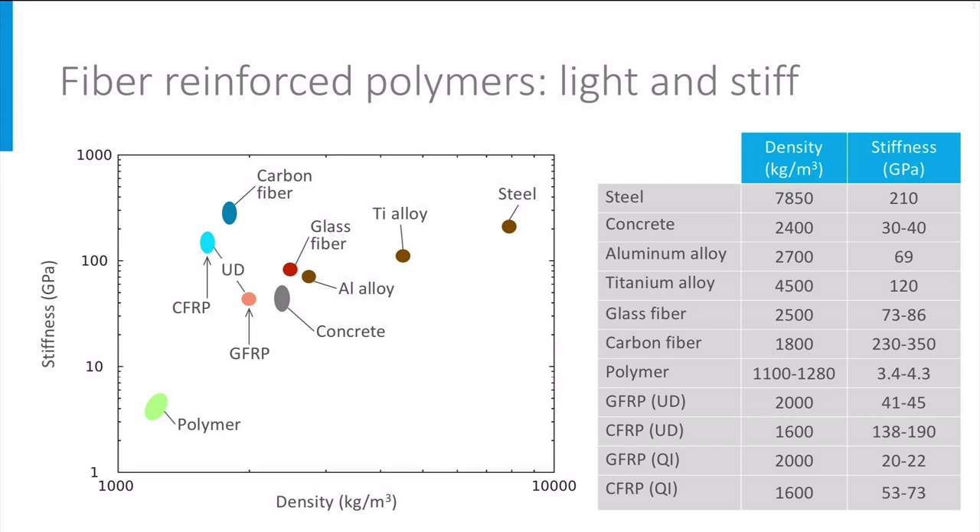This is not the end of the story. These properties are for unidirectional FRP composites that have low stiffness and strength in a direction perpendicular to the fibers. To mitigate this weakness, laminates are made — layered structures with different fiber directions in the different layers. Depending on the application, the fiber distribution can be UD-dominated or it can be such that the laminate has equal properties in all directions. This last extreme is obtained with a quasi-isotropic layup. If we also include the quasi-isotropic layup in the chart, we see that the performance is less impressive. For a real FRP design, the stiffness in the primary load-carrying direction can be in between the UD and the quasi-isotropic values. A stiffness in one direction that is higher than the quasi-isotropic one is going to have negative consequences for the stiffness in other directions, which will be even lower than the quasi-isotropic value.